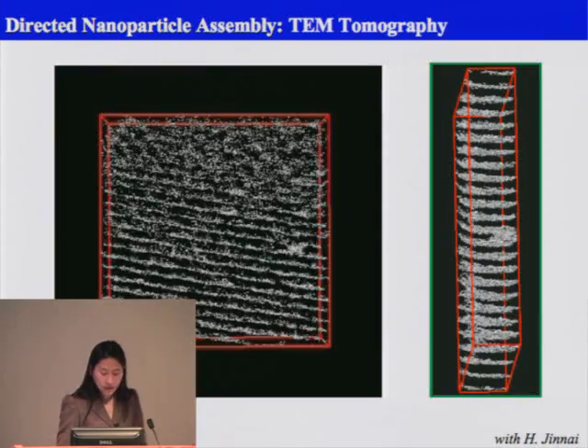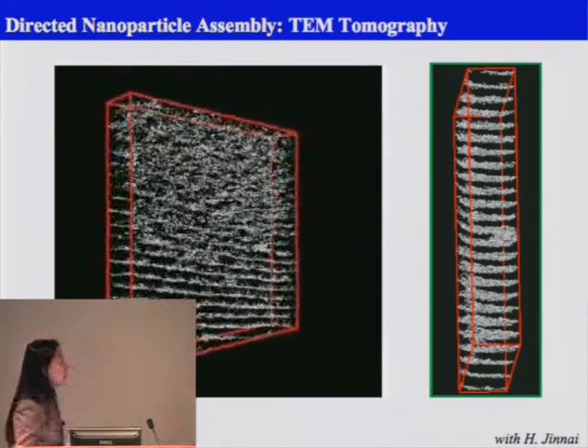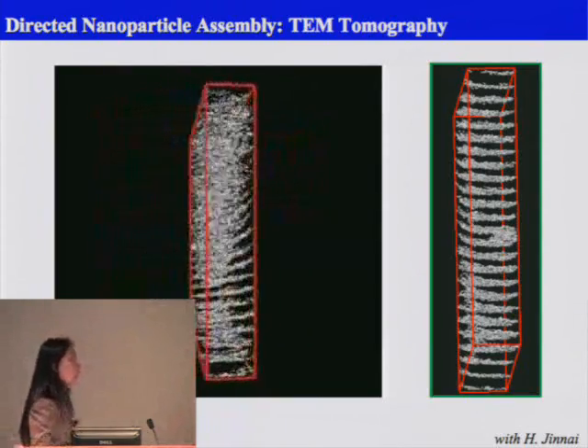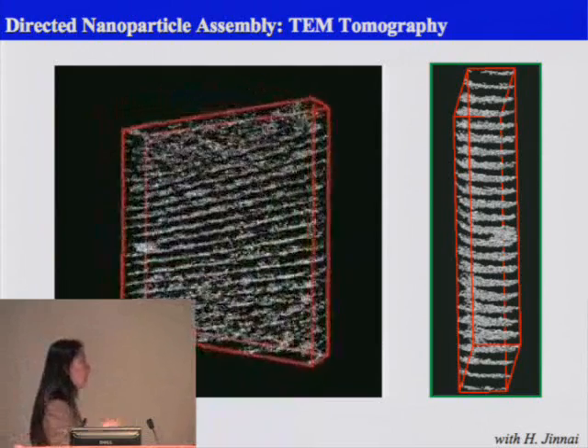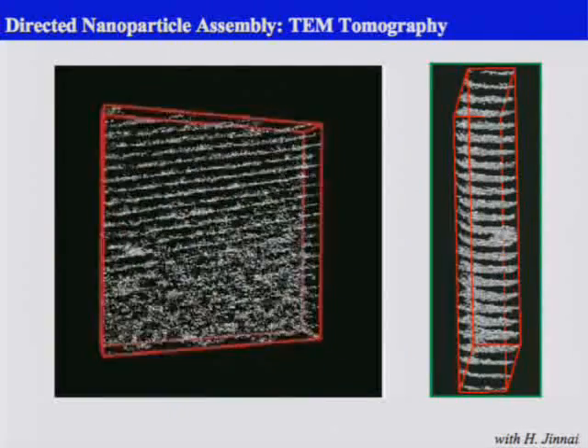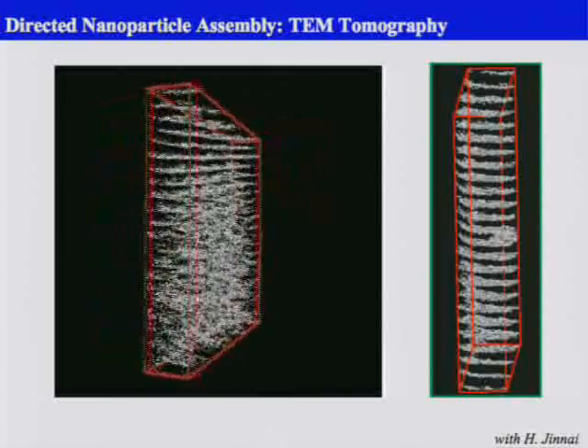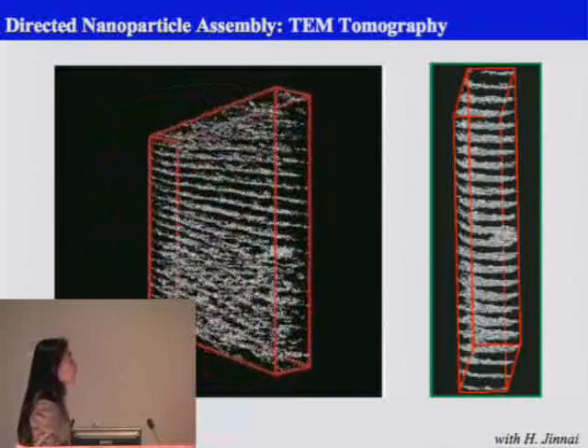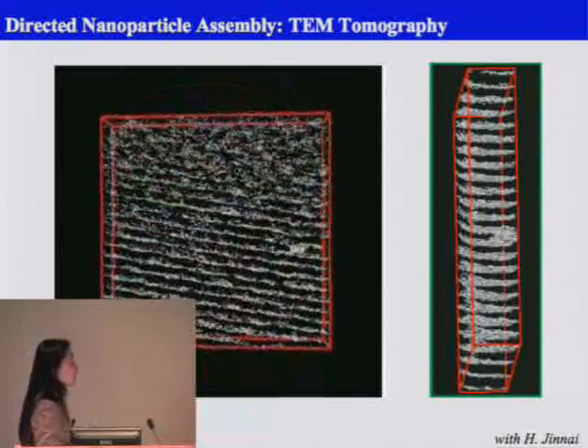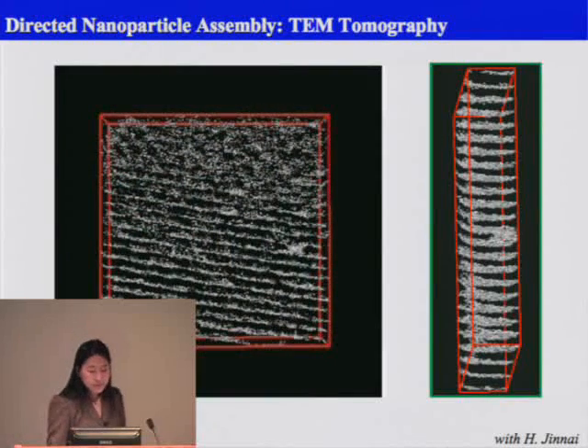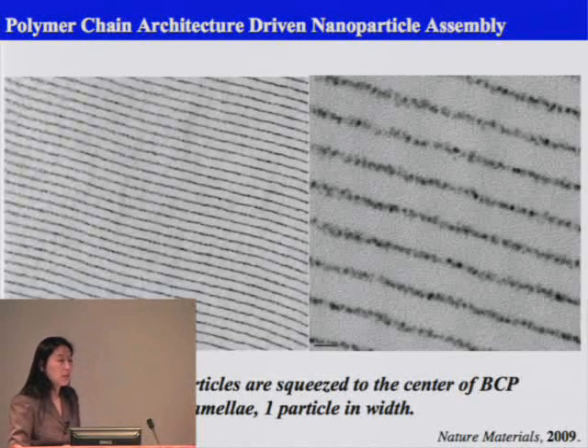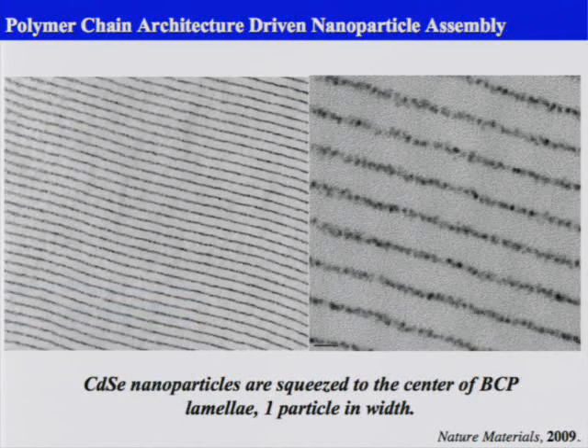This is one of the TEM tomography images showing that indeed we can incorporate the nanoparticle into the block copolymer with assistance from the small molecule, and you can see it forms lines and sheets of them. If you look at the TEM image, you can see how nicely you can control the particle ordering. This is just a cross-section of the TEM image.